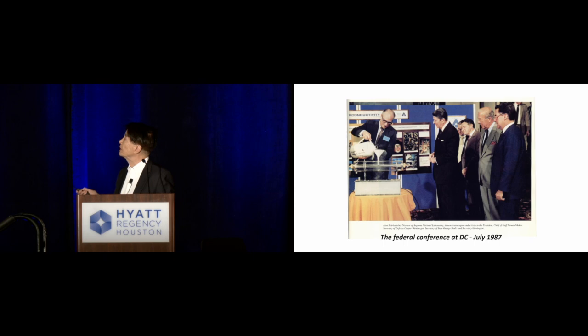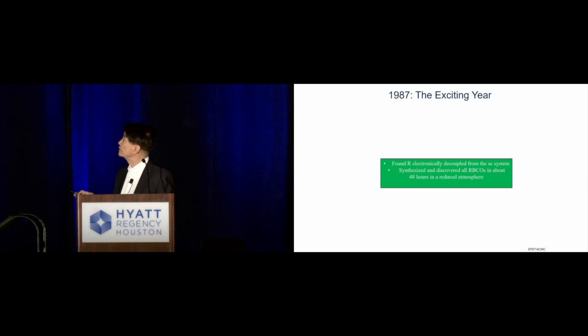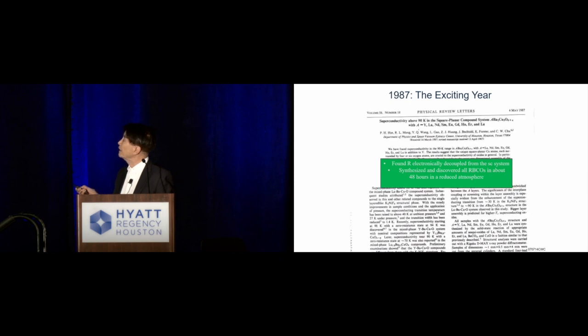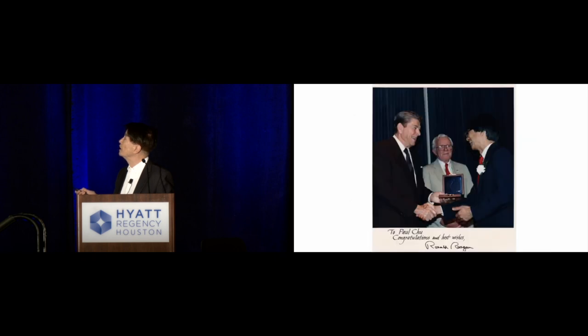As you can see, the president saw the demonstration by the Argonne National Labs director himself here, and that was the first time people could really do a demonstration like that. Prior to that time, to do the demonstration, you had to use liquid helium. It's very difficult. So then with that discovery, we immediately discovered a series of compounds which all have TC higher than liquid nitrogen temperature. And so finally, President Reagan decided to give me the National Medal of Science, essentially to represent the whole field working in high temperature superconductivity.